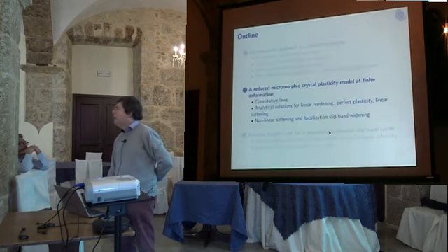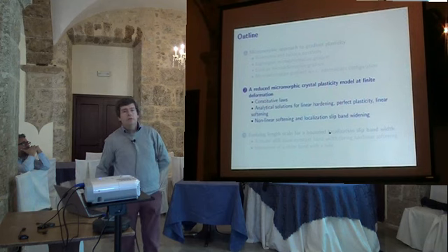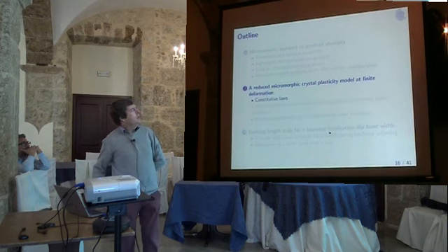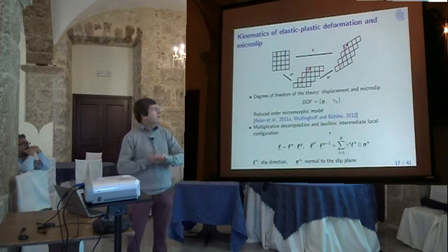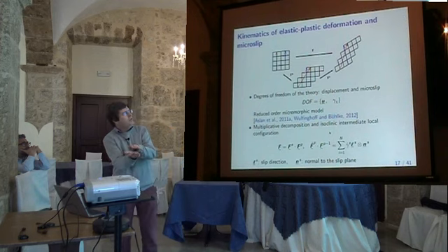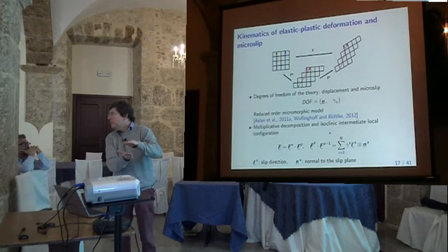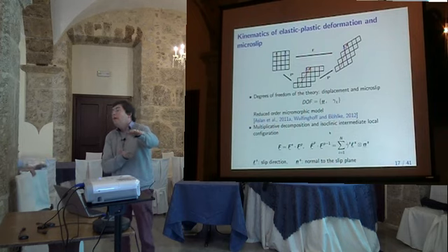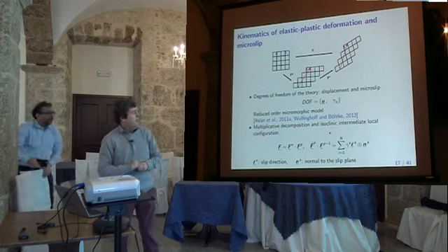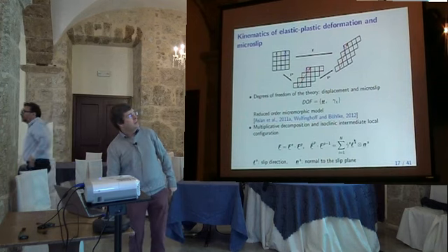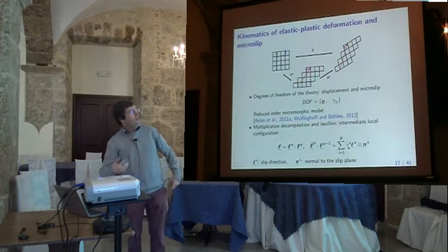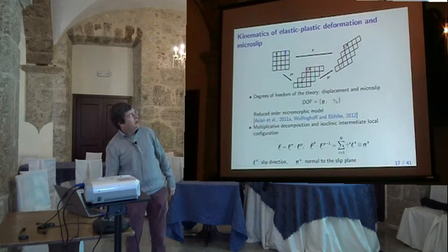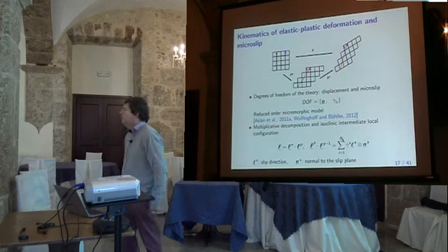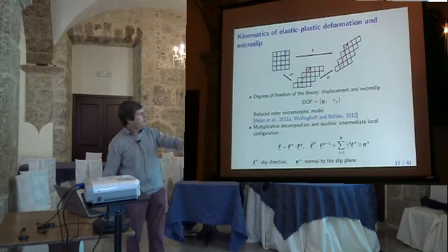Let's apply this now, because this was only the framework. Let's apply it to a case where I will consider a single crystal because I simply want to consider slip on a slip plane, one single slip system. So it's a bit like a pure shear band. This is what I want to study. And then the plastic flow is due to slip systems. And you have the gamma here, which is the amount of slip. And I will take capital N equal to 1, only one slip system. It's even easier. Okay, so this is the same structure.